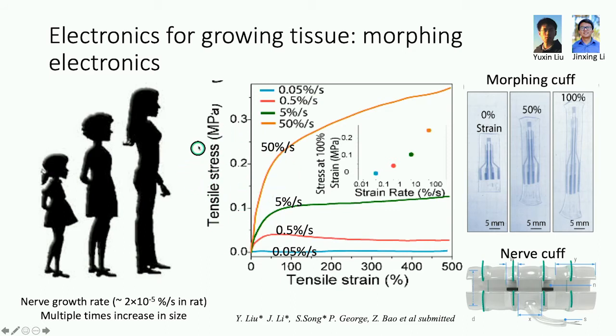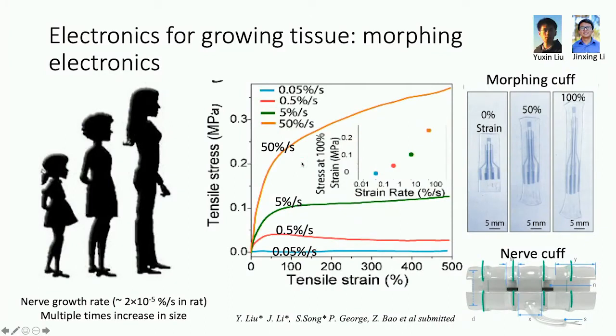that's applied to these materials, and this is the tensile strength. And then with these materials, we can fine-tune them, both the conductors and the substrate themselves, so that when there's a strain applied very, very slowly over time to mimic the growth of the nerve, then essentially there's no stress being applied to the nerve. And if you have movement of the person, in that case, the material can behave more elastic and recover its original shape. So it can accommodate the movement, but while at the same time, with short time scale, it can conform very well with the nerve.